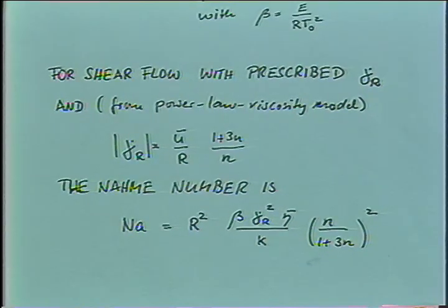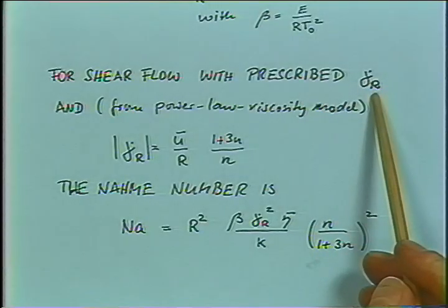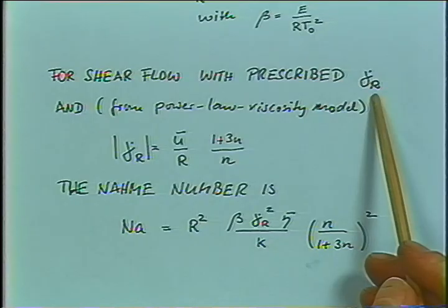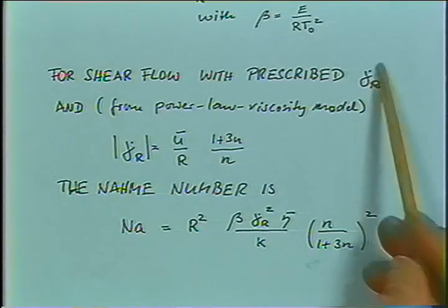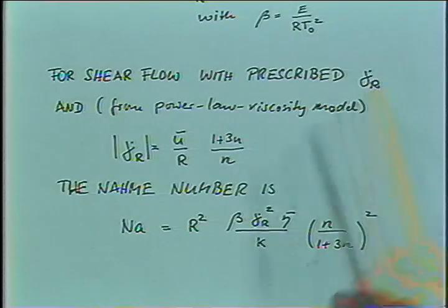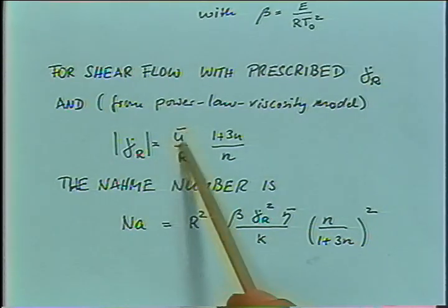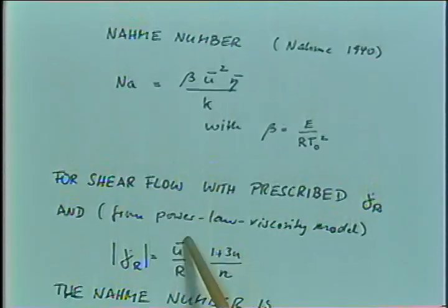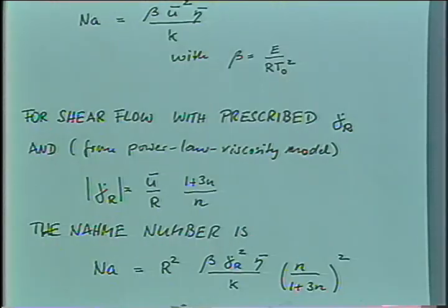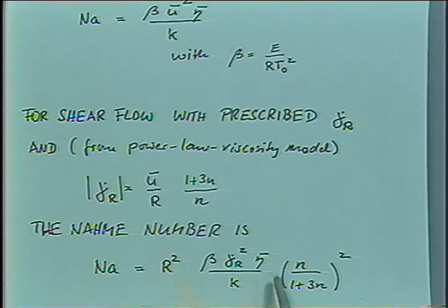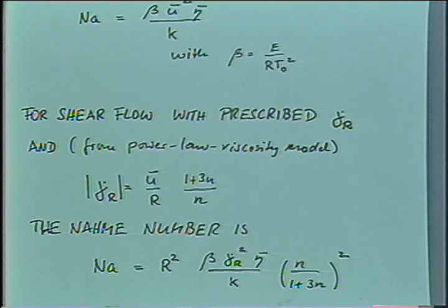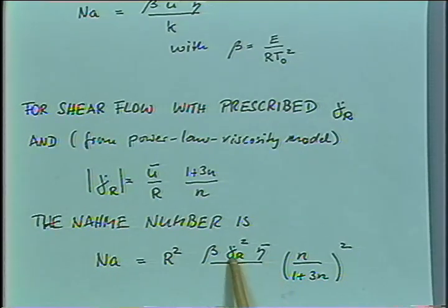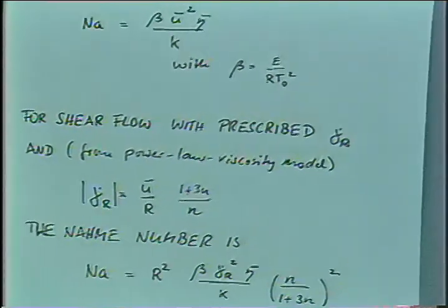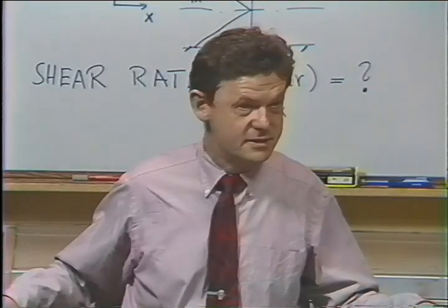For our case, we would prescribe the shear rate. We would say you want to know the viscosity at 1,000 seconds to the -1. So that's normally prescribed. And with that shear rate and a power law model, we would be able to calculate the average velocity in the capillary, and we introduce this average velocity in the Nahme number and find that the Nahme number goes with R squared times some coefficient, which we cannot influence very much, is given by material properties, and the shear rate, which is prescribed, and the power law coefficient. So the bigger the radius, the bigger the Nahme number, and you saw that in the experiment. It's coming really right through this viscous heating effect.